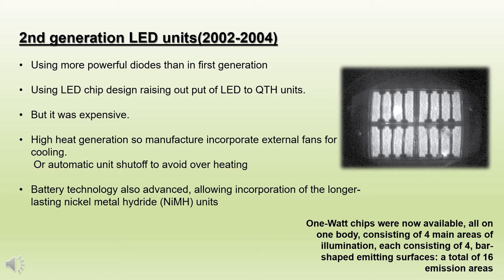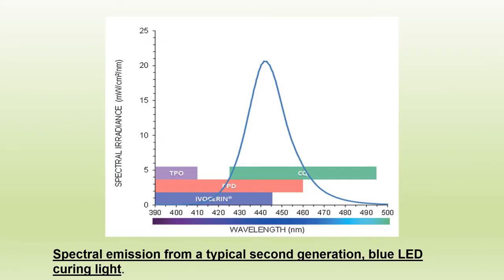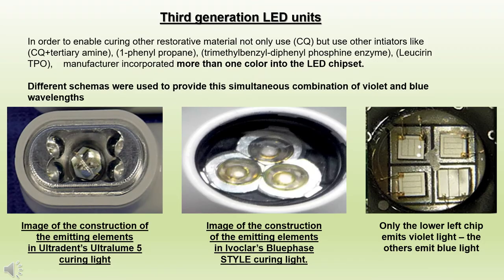However, with the increasing need to dissipate thermal power from the higher-rated LED chips, advanced methods such as internal fans and large metal heat sinks were used to remove the heat from the LED arrays. In order to enable curing other restorative materials, not only those using CQ but those using other initiators like CQ plus tertiary amine or Lucerin TPO, manufacturers incorporated more than one color into the LED chipset. This generation of LCUs is also referred to as multi-wave or multi-peak LEDs because they can emit light of more than one color or wavelength range.